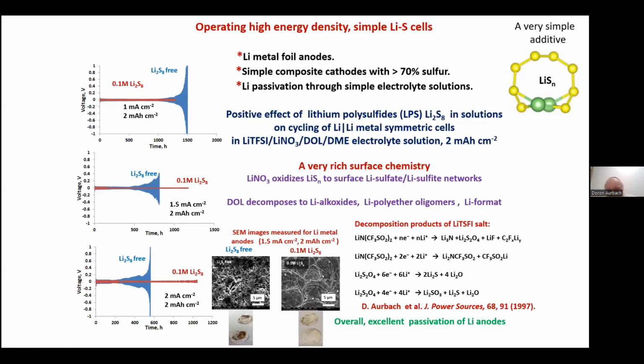We demonstrated that if we use the conventional electrolyte solution for lithium-sulfur batteries, this is, by the way, an electrolyte solution that we discovered. We worked a lot with lithium metal based batteries with this electrolyte solution, and we demonstrate that dioxolane is a very good solvent. There is unique surface chemistry. You can see it here. The dioxolane is reduced to different compounds, and there is the salt anion. This also is being reduced to several compounds, and we have very complex surface chemistry.